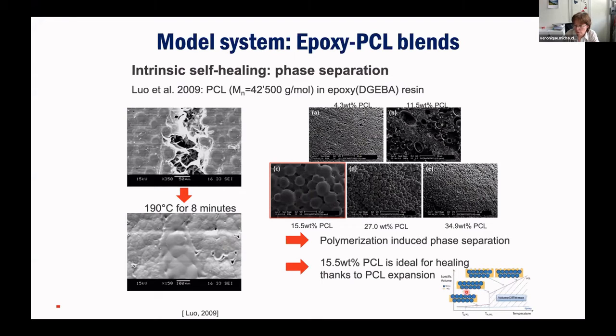And they also saw that what was really interesting with the PCL is that you have a phase expansion that is quite good. So if you look at the volume difference when you pass here in the temperature, the melting point of the PCL, you see that the PCL tends to expand quite a lot, about 14%, and then it will start to bleed out. So you need this if you want to have enough bleeding.